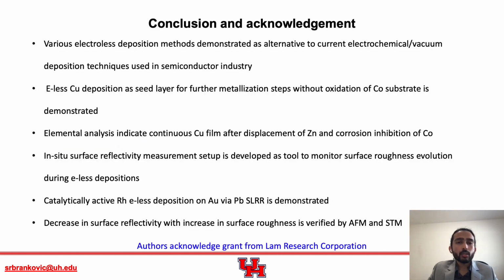So to conclude this talk, in general, we have demonstrated various electroless deposition methods which could serve as an alternative to current electrochemical or vacuum deposition techniques which are being used in semiconductor industry. For the first project, we have showed that electroless copper deposition on the cobalt substrate by replacement of zinc can serve as a seed layer for further copper metallization process. And elemental analysis indicate that there is a continuous copper film after dissolution of zinc. And we have also demonstrated corrosion inhibition of cobalt in the same system.